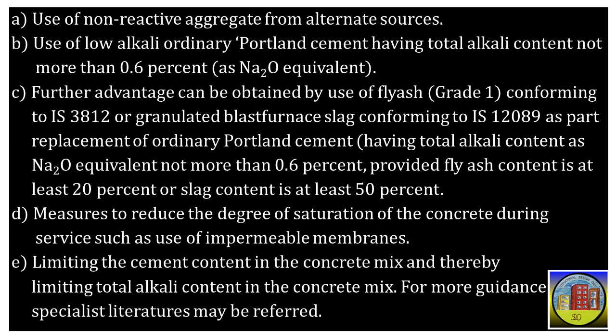C. Further advantage can be obtained by use of fly ash, grade 1, conforming to IS 3812 or granulated blast furnace slag conforming to IS 12089 as part replacement of ordinary Portland cement, having total alkali content as Na2O equivalent not more than 0.6%, provided fly ash content is at least 20% or slag content is at least 50%.